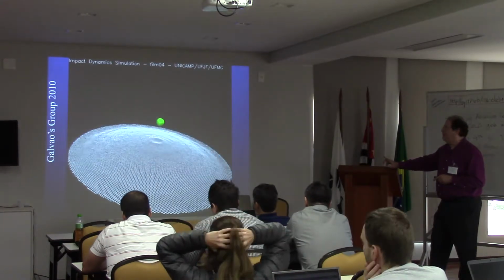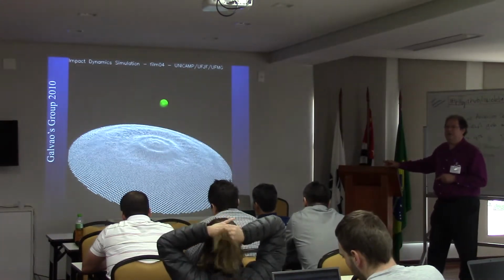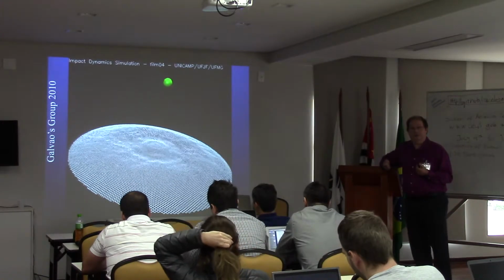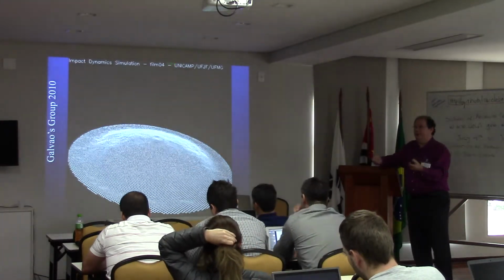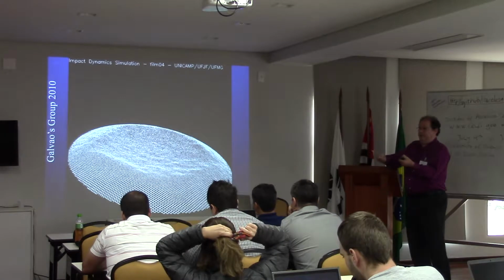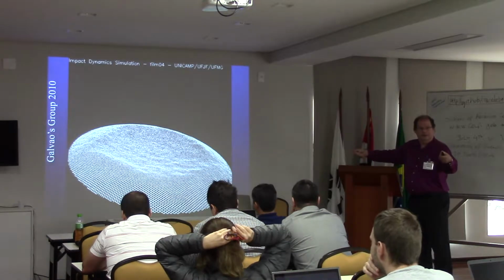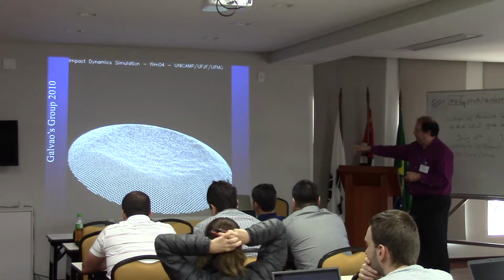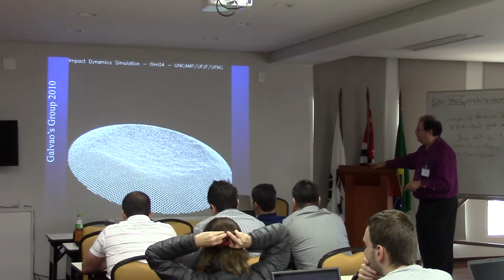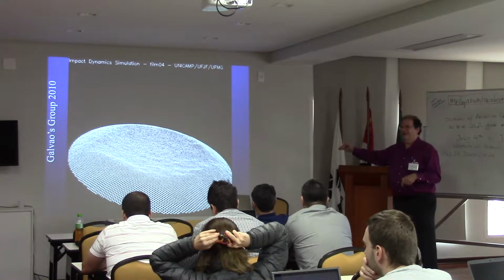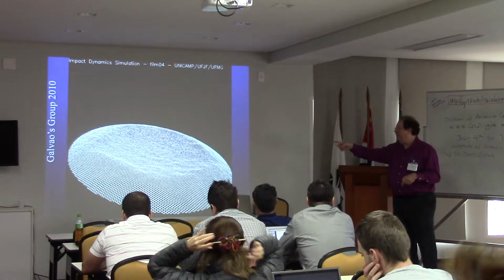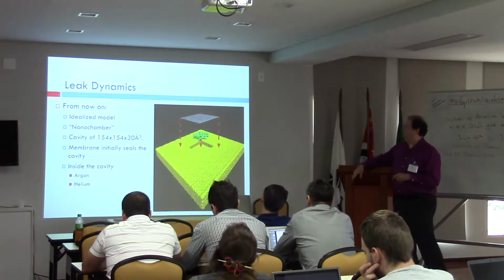But again, people are concentrating on the electronic part, but graphene itself is a very amazing material from the mechanical point of view. It's the strongest material to break, even stronger than diamond if you try to break along this direction. See? In this case, you see the propagation is almost a textbook elastic wave. You see reflection on the border. Okay.